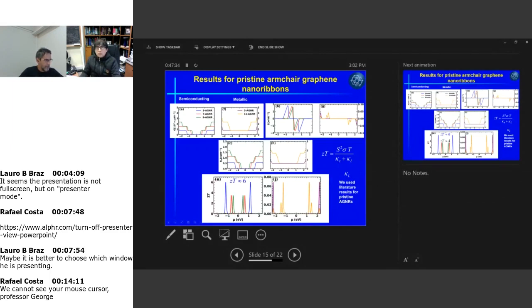So the results here are only approximate. You can see that we have ZT of the order of 6, and ZT of the order of 5 or 4, depending on the width of the nanoribbon. And clearly ZT decreases with the width of the nanoribbon because of the increase in kappa L. The wider the nanoribbon, the more efficient the phonons are in transporting energy, in transporting heat. So kappa L increases and ZT decreases. And we can see on the right side, in panel J, that the ZT value is very, very low. It's two orders of magnitude smaller because the Seebeck coefficient of a metal is very low.